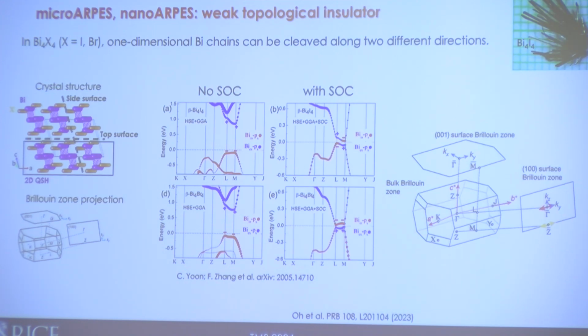But basically, this class of materials, bismuth halides, Bi4 either iodine 4 or bromine 4, are weakly coupled one-dimensional bismuth chains. And the nice thing about these is that this is basically the crystal structure. You can see that these are just chains that are stacked in both dimensions. So naturally, you can cleave the crystal either in this way, which will expose the 001 surface, or it turns out that you can actually cleave them this way, which will reveal the side surface, or the 100 surface.